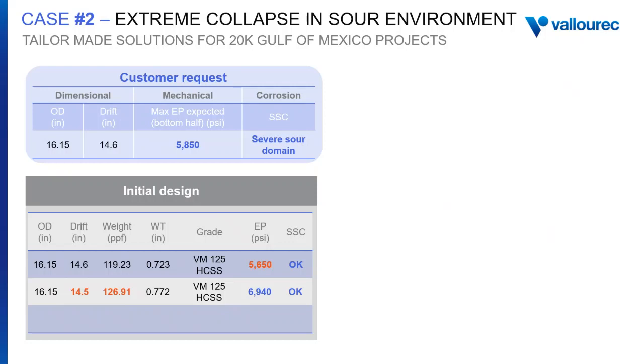This resistance could be enhanced by increasing the wall thickness. We see that by moving to a 127 pounds per feet, the collapse resistance is increased to an acceptable value of 6,940 psi. However, this alternative is not acceptable by the operator since the drift was reduced to a value that could severely complexify the drilling of the next section.